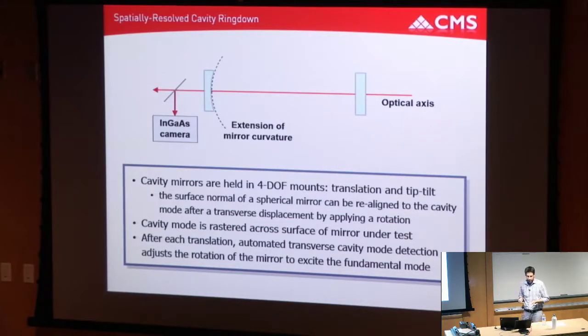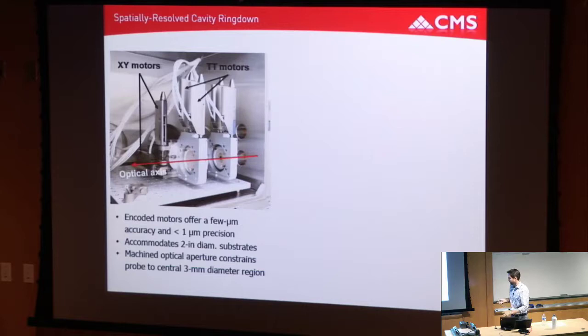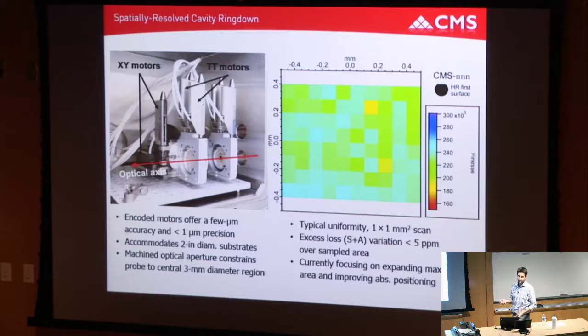Then our scanning ring down system: we have a very nice staff member, Garwing Truong, who came from Nathan Newbury's group at NIST. And he built this very cool scanning ring down system for us. So we basically have the two optics, say planar and curved, and we will displace the curved optic, then pitch it back into alignment with the planar optic and maintain the fundamental mode of that cavity. And we can now do scanning ring down on the system. It's in a vacuum chamber with these X, Y, and tip tilt mounts. And Garwing has a really nice program to automatically scan the optic and generate these 2D maps of finesse as a function of position. And from this, we can pull out bounds on the optical loss.